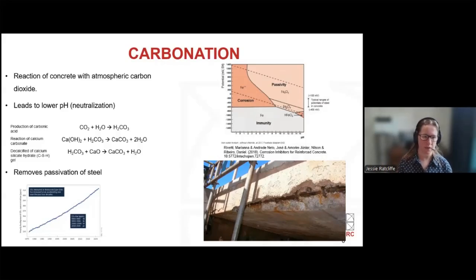So the original high pH is what protects your steel and passivates it, preventing that corrosion from starting. It's illustrated on the right here in the Pourbaix diagram. You can see in the potentials for steel, we have a passive section that correlates with the pH of concrete, and as we move left, we have that chance of corrosion.